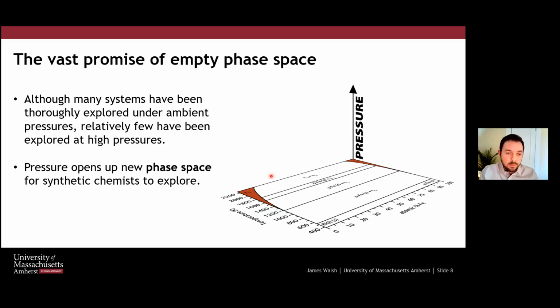Well, the answer is you expand your phase space. You find some other parameter that you expect should have an effect on synthesizability, and you use that as your synthetic variable. And so that for us, it turns out, is pressure. So I did originally start looking in the iron bismuth system, trying to make new iron bismuth compounds using other techniques that have been shown to be able to access metastable materials like nanoparticle synthesis. Electrodeposition didn't really go anywhere. Pressure turned out to be the key. And so that's really why we now talk about it. And I don't talk about nanoparticle synthesis.